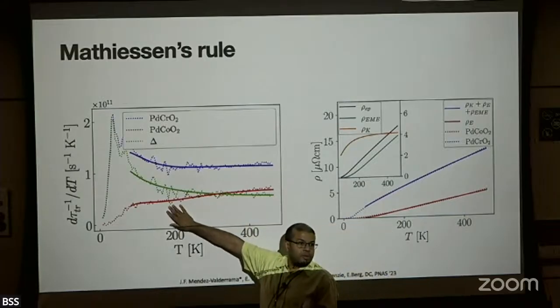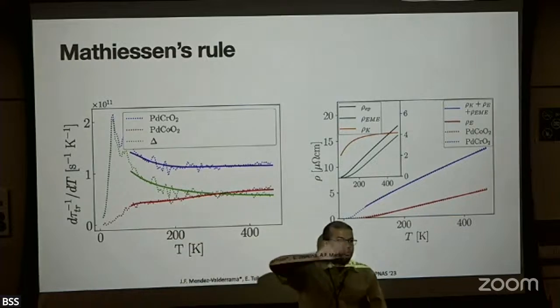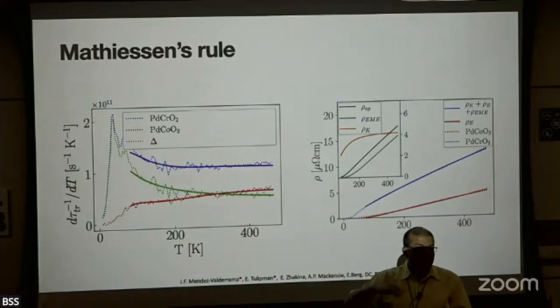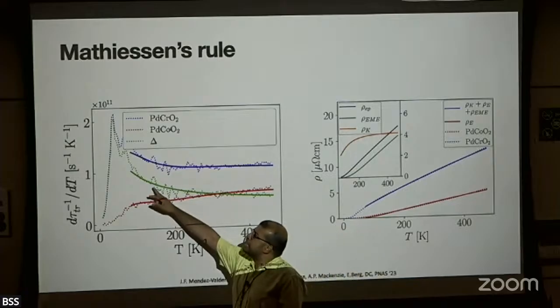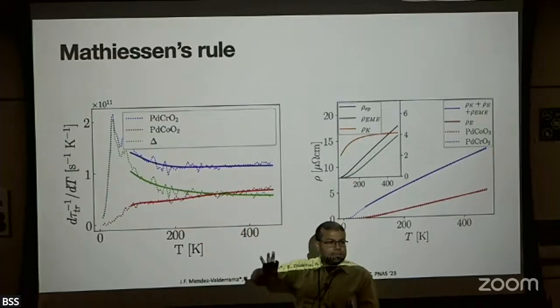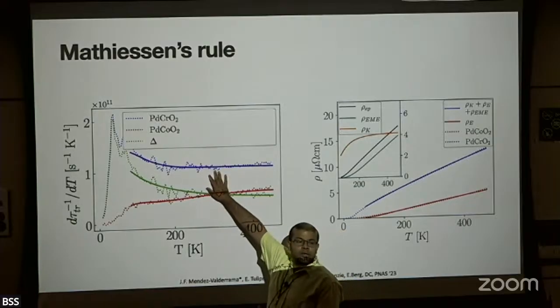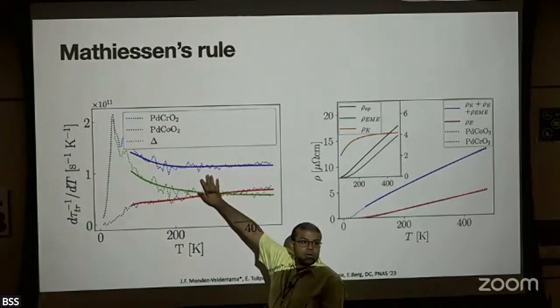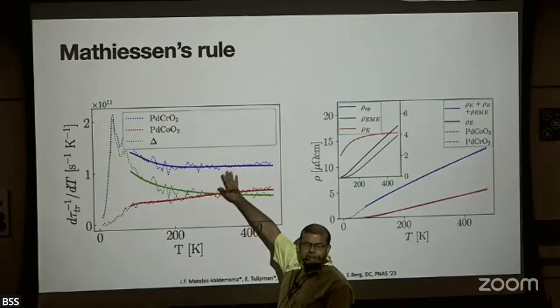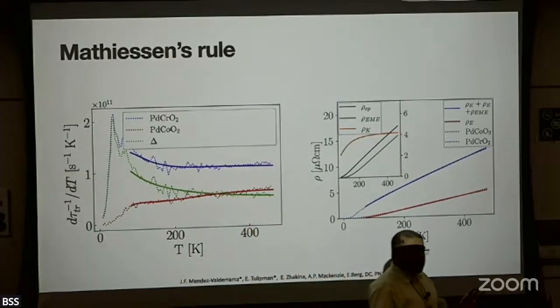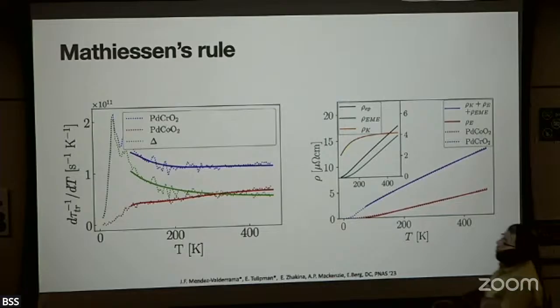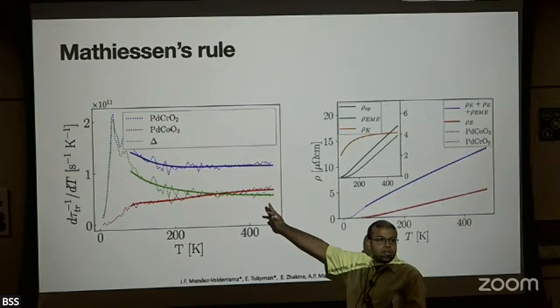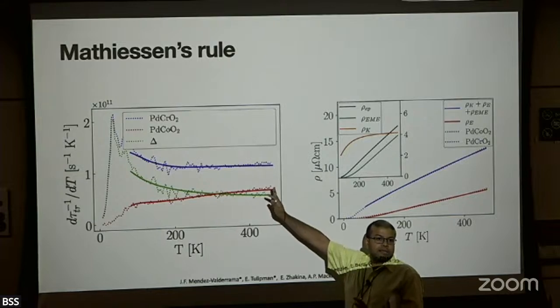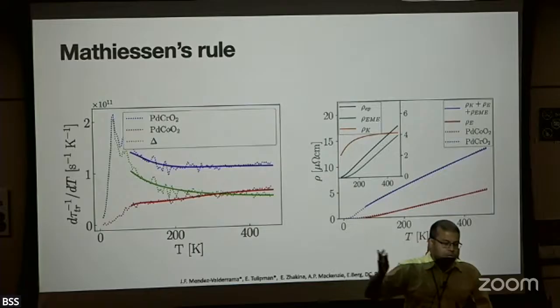Actually, we understand exactly where this is coming from. This is due to coupling to two phonons, one of which is in the high temperature, the other one is not. The green is the difference. And miraculously, when the two add up, that's what the scattering rate in palladium chromium oxide looks like. And this is the one that's almost linear with this Planckian value. So for some remarkable accident or maybe some deep underlying principle, it's as if all these scattering rates add up in a fashion that gives you this Planckian scattering rate, which is T-linear, which of course we don't understand.